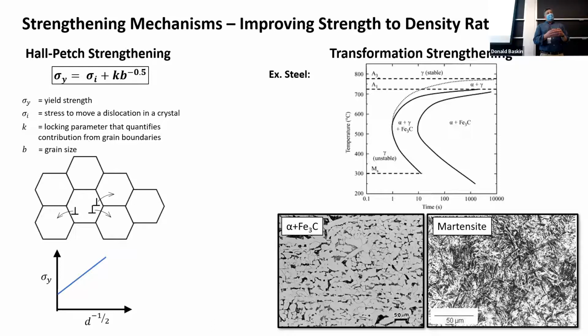Part of that will transform to what's called martensite. Martensite is body centered tetragonal. And because of the thermodynamics, it's got that really tight little needle structure, these kind of interlocking, tiny nanoscopic needles that interlock with one another. Call them martensitic laths. It's another subsystem of the microstructure. They're very strong. It's very hard to get a crack to propagate through that stuff, or a dislocation to move through it. So there's an example where you've gone from ferrite to austenite to martensite, and the martensite is much stronger than the ferrite. That's an example of phase transformation strengthening.